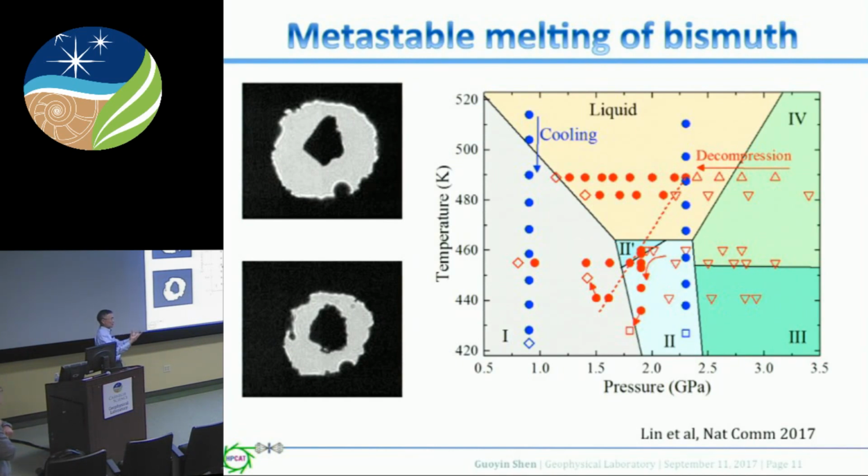That's, of course, accumulated from the literature data. I think if you fit a thermodynamic model to all of your data, you might be able to know where the rest of the lines go. In general, I would think mapping the metastable phase diagram is going to be much more challenging experimentally, because as we showed, nucleation as well as the stress environment is going to affect all the pathways. That's why we use the equilibrium phase diagram, so we always know exactly where the transitions are.